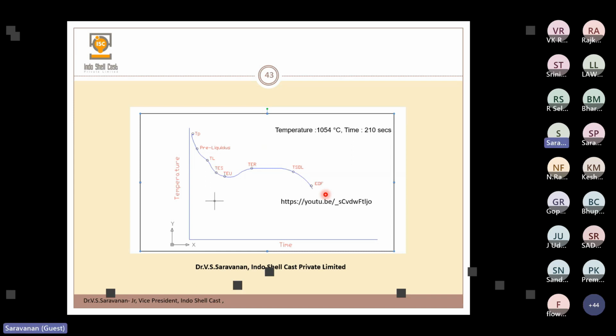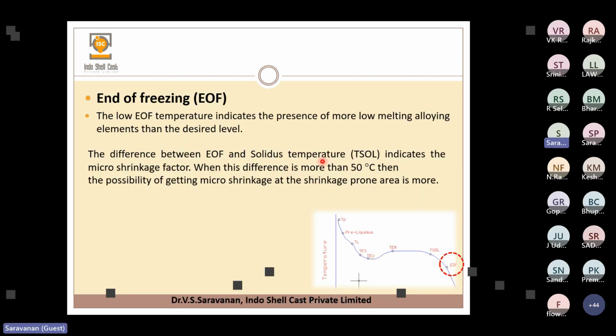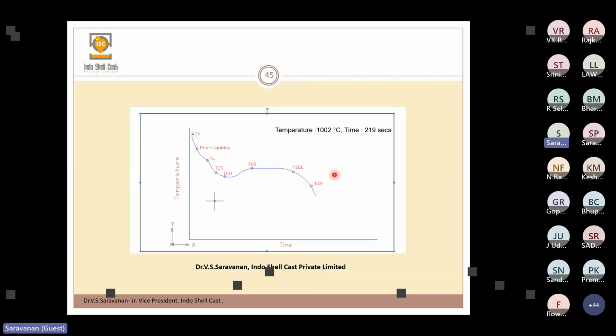So we should be very careful in adding the low melting alloys. Mostly, we have to adjust the metal to achieve the mechanical properties by adjusting the carbon and silicon. That is very important here. Here, the difference between the end of freezing temperature and T solidus, when it is more than 50 degrees centigrade, then there is a possibility of getting micro shrinkage, because more low melting alloy is segregated at the grain boundaries, and then there are chances of micro porosities. So that is the end of freezing.